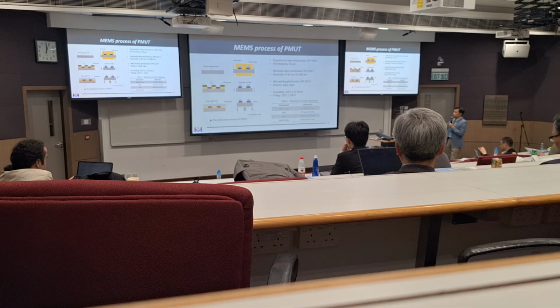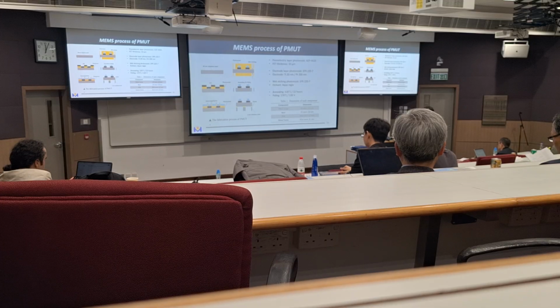techniques. We are using photoresist, so we can do lift-off for the PZT deposition, and the PZT layer, the piezoelectric layer, we fabricate using the aerosol deposition method that's also developed in-house. And then we also do wet etching to define the final outline shape. Then we need to do annealing to activate the piezoelectric layer, and of course we also need to do poling to activate the piezoelectric property. Okay, so this is the final dimension. The final dimension of our PMUT array is 25 millimeters by 20 millimeters.